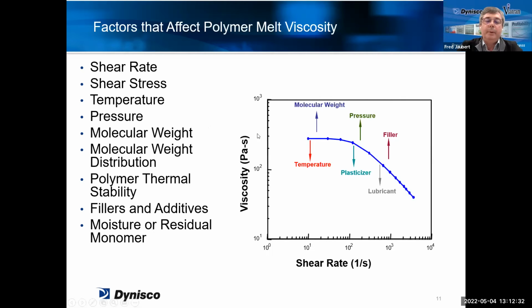And now, why are we checking this viscosity, and what is the use of these viscosity curves? If you plot various viscosity curves of the same polymer, you will see that they are not always matching together. So you will have some differences. As you see on this graph, depending on, for example, the molecular weight, if the molecular weight is increasing, then the curve will be higher. This seems obvious because if you increase the molecular weight, the product is more viscous, so you are going higher.